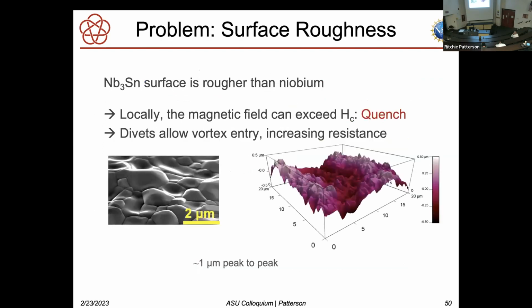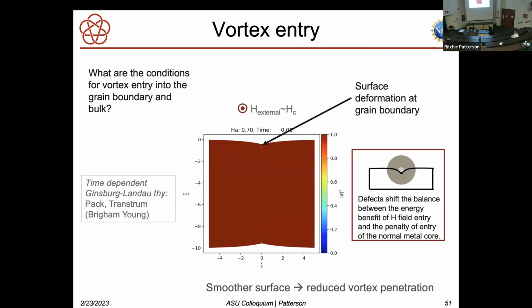One is surface roughness. Niobium-3 tin surfaces, when you look at them closely, look like this. They're quite rough. And that means that locally, the magnetic field can go higher than what it is on average. And remember, our accelerating gradient is limited by that. Also, the divots let vortices enter the body of the material. And here's a little simulation that we've done of that.